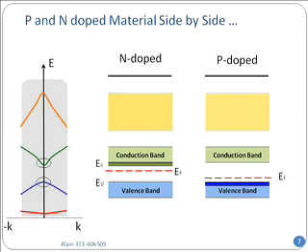Actually, nothing will happen. Because of these surface states that we talked about, there are actually in every material lots of surface states. And when you bring the two materials together, the surface states will eat up all the extra electrons. There will be no electron transfer from one side to another. That is why you cannot simply bring an N material and a P material and sandwich them together to get a p-n junction diode. That's not that easy. Then it would have been done many years ago.